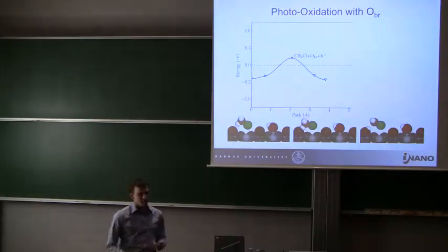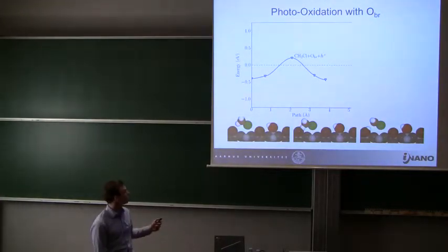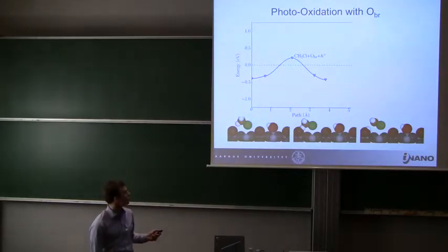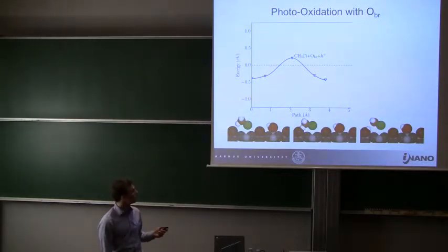So that seems to be the mechanism for this photoreaction. Finally, when we have transferred the proton completely, we get into a p-state in the band gap that corresponds to the hydrogen. But of course, it's the energetics that decide whether this reaction is possible. We see that at the transition state, we are actually well above the adsorption energy of this molecule, which means that it could not really happen on this surface. So we need to look into some of the other proton acceptors.